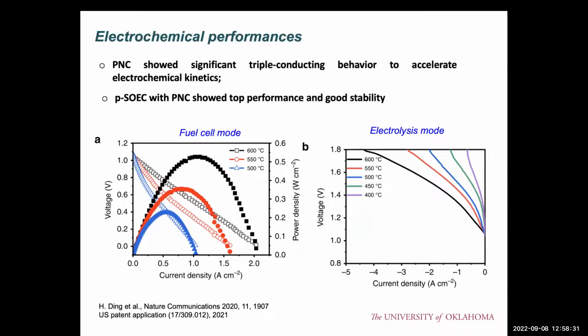Here, this slide shows some typical performance of your fuel cell and also electrolysis mode. If you multiply the current density and the voltage, you can also form the power density. We compared this power density with others to demonstrate the advance of the materials development. On the left side of figure A, you can see the intercept is about 1.1 volts. That's the open circuit voltage for the SOC. In order to facilitate water splitting, you need to apply the external circuit, so we need to have the voltage above this open circuit voltage.